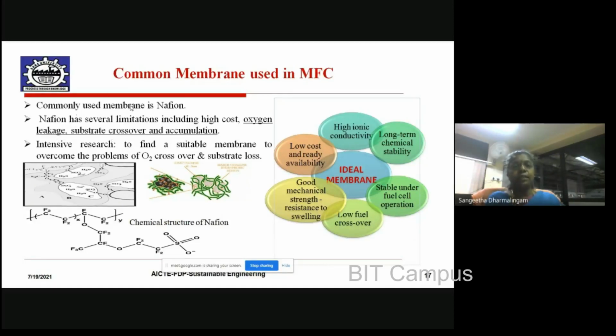And then the substrate crossover and the accumulation. Okay, this accumulation is nothing but the protons without getting transferred. If it is biofouled, if the crossover of oxygen is too heavy, then the protons are not able to transfer, which is otherwise expected to happen in the efficient working of the fuel cell. So the protons get accumulated in your anode, and they make the entire situation more and more acidic because of the presence of the H+ ions, because they are not transferred to the cathode. The condition is not conducive enough for the organisms to grow and do their functioning of consuming the food and producing the electrons. Therefore, it becomes a complete failure when Nafion membrane is used.